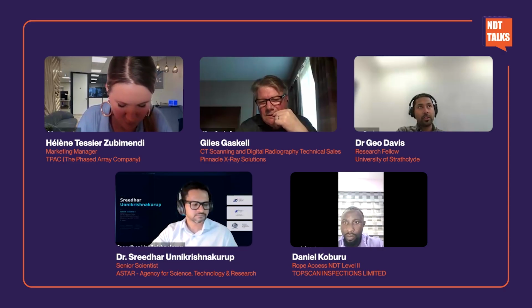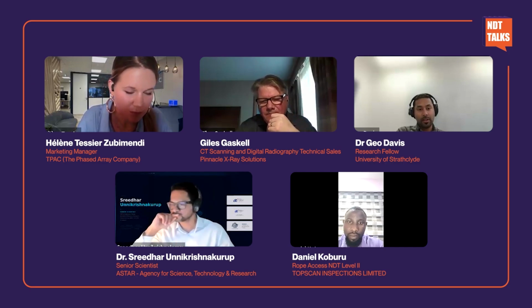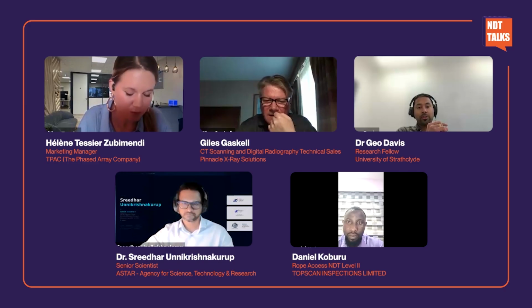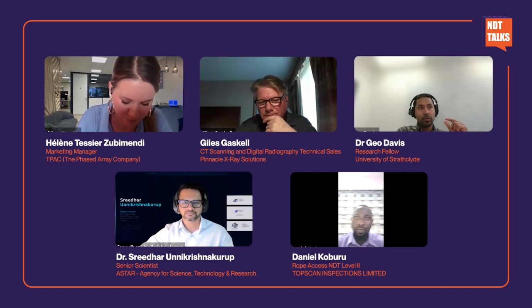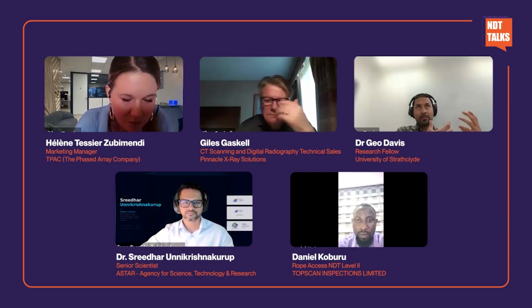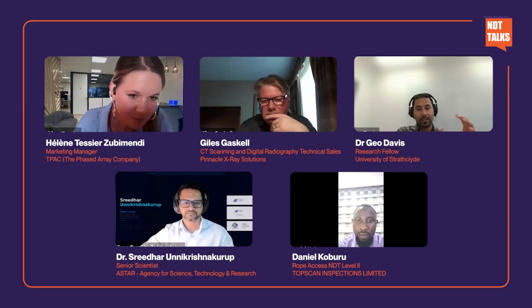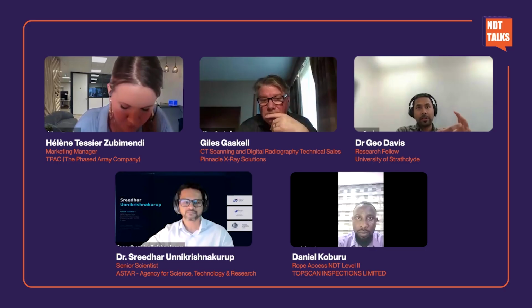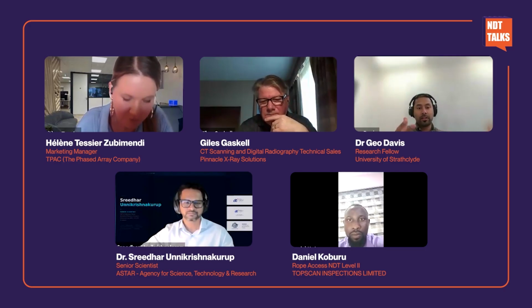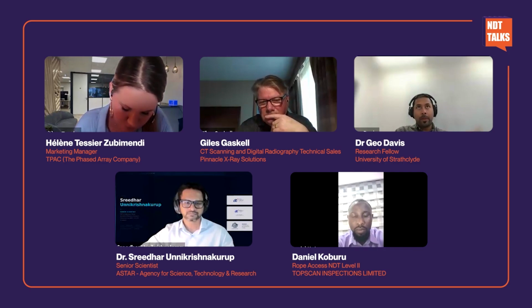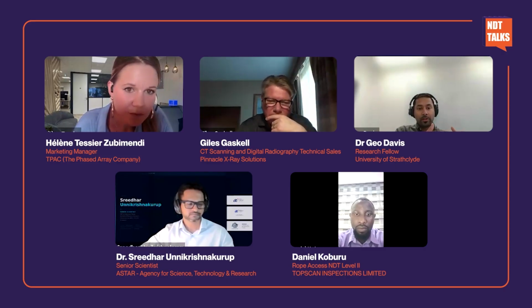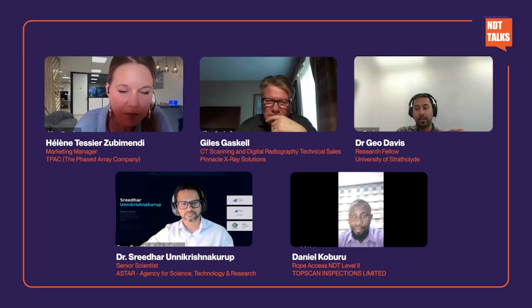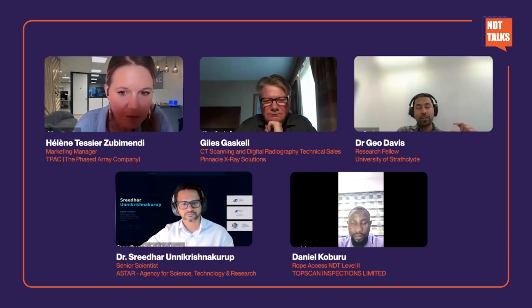I think the advantages and limitations of these techniques come from the resolution of how small a defect you can image. XCT, again, we said it's a gold standard. You can detect submicron defects like porosity, but the limitation is you can't use it for all metals because density is the factor there. You can't really inspect highly dense materials. So there's a difference between the density and the thickness of the material that you can inspect. For ultrasound, you can go to hundreds of megahertz, but useful information is within the first 20 megahertz, is what I understand. And for eddy current, the limitation is that you can't probe deeper into the sample. It's mostly surface or near surface.